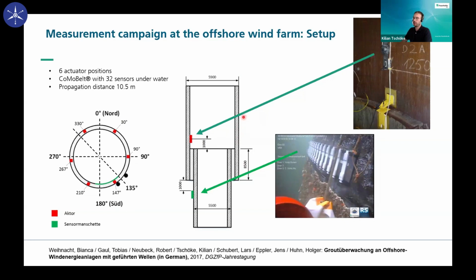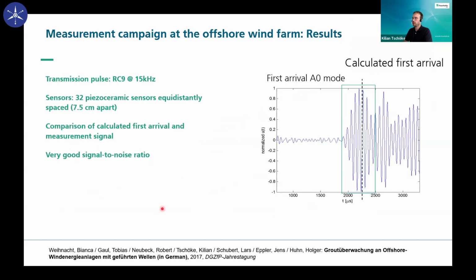So the tower itself is also like a big pipe, or this transition platform is also like a big cylinder with a diameter of approximately 6 meters, as you can see here. We have 8.5 meters of grouted joint, which is the area of grout and the connection between these two pipelines. And then 1 meter from this transition area, we've installed the sensor belt with 32 sensors. So this is maybe, let's say, the extreme case for using guided waves, but we were able to measure guided waves with the sensor belt underwater. So by using an installed transducer in the access area of the monopile, and by using the sensor belt underwater, we are able to monitor this joint connection between tower and monopile.